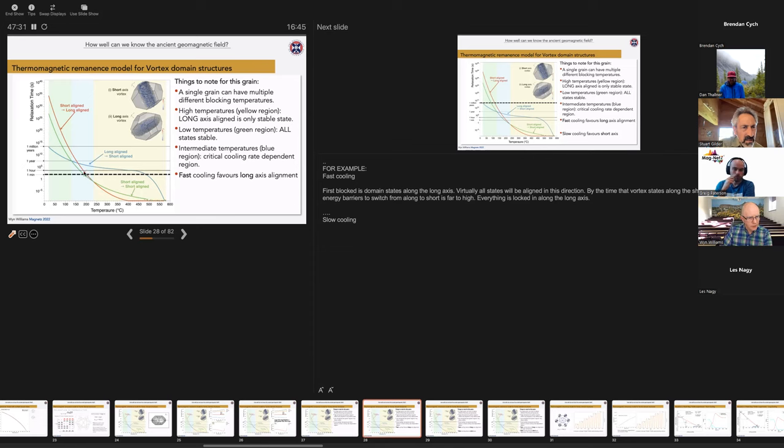So one thing I would like to explain if I just have a few more minutes is both the Arai plots exhibit high temperature PTRM hooks shown by this green region caused by a peak in the PTRM gained between 200 and 300 degrees centigrade and a decrease at high temperatures subsequently. And this can be explained by examining our relaxation phase diagram. As we put in PTRMs at increasing temperatures, we first activate the grains that are aligned on the short axis. As we heat up from below the first grains that we reactivate that become unstable are the short aligned grains. And then these grains will transit to long aligned axes, which have larger remnants. And so we get an increase in the PTRM peak at around 200 to 300.